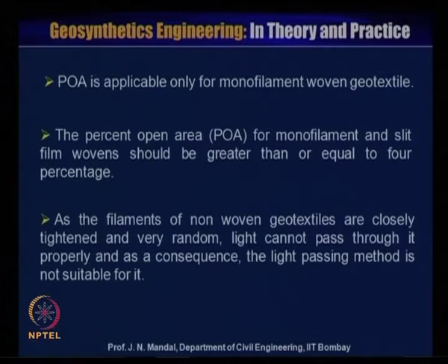As the filaments of non-woven geotextile are closely tightened and very random, light cannot pass through it properly, and as a consequence the light passing method is not suitable for it. So, it is preferable to perform the test for the woven geotextile rather than the non-woven geotextile material.